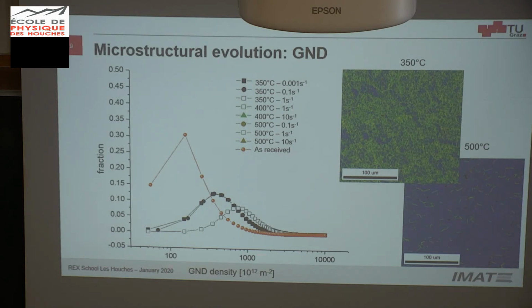So here is the geometrically necessary dislocation density. In this direction, you go to higher values of dislocation densities or stored energy, however you want to see it. So in this direction we are increasing, with lower strain rate to higher strain rate, so we increase the stored energy. When we go to higher temperatures, we go in the other direction. This is very typical. You will see this not only for large strains but also for low strains. You will increase the recovery at higher temperatures in this direction, and you will increase the stored energy in the other direction.